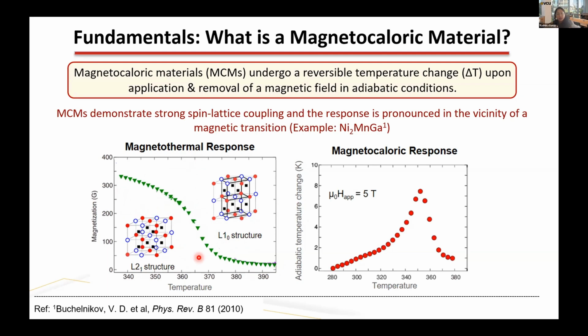And exactly at this magnetostructural transition temperature, if you were to apply a magnetic field and remove it, a magnetic field of strength 5 Tesla, you would see an adiabatic temperature change of around 8 Kelvin. So this is a classical example of how a magnetocaloric material works.